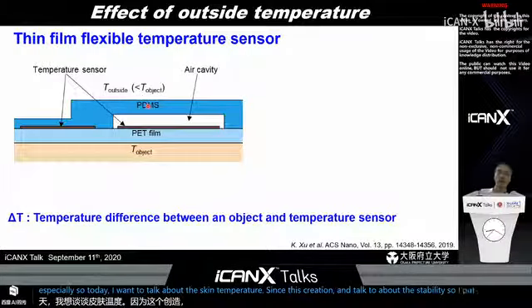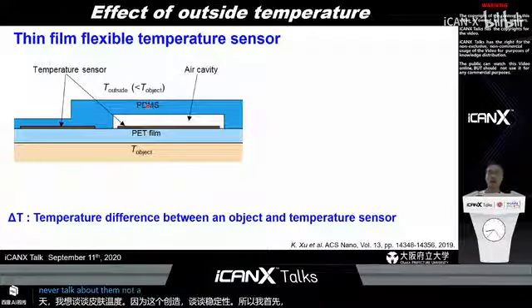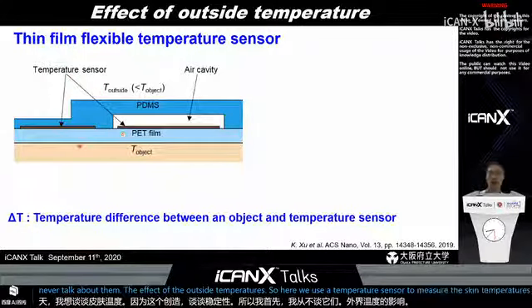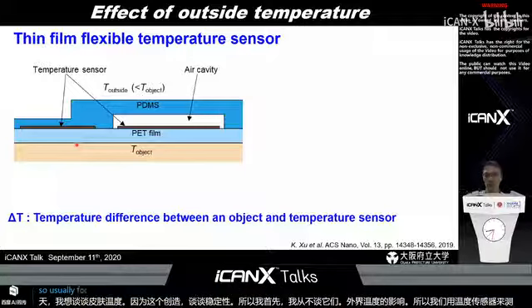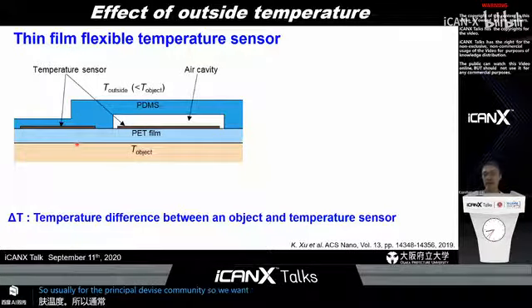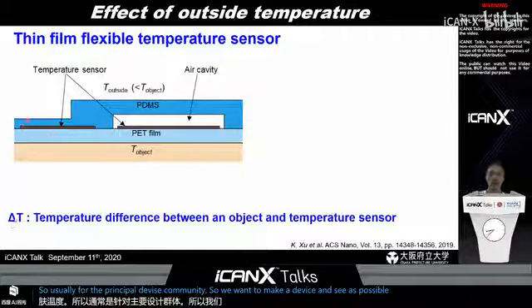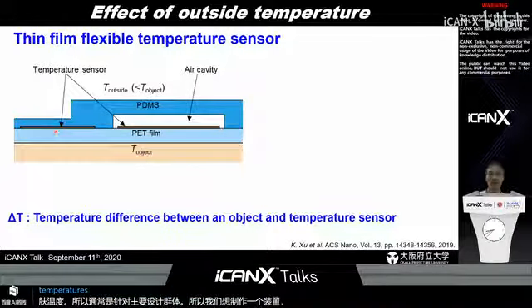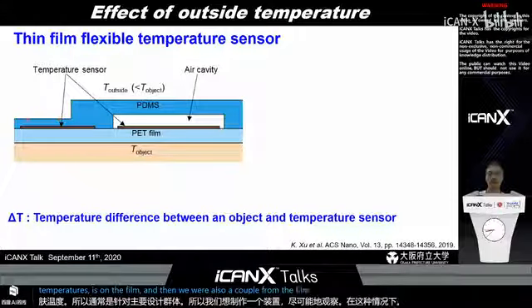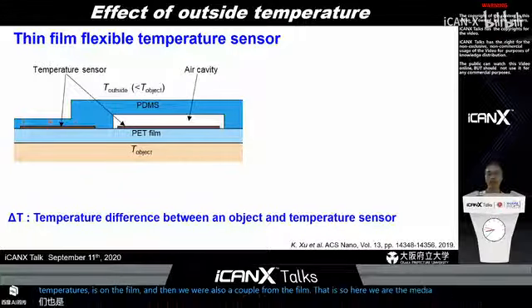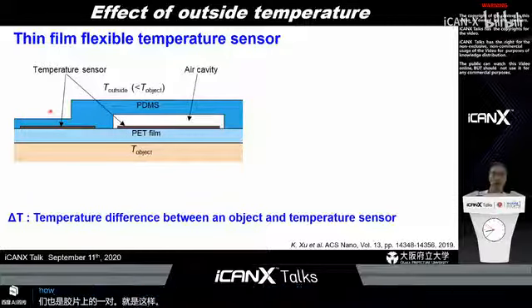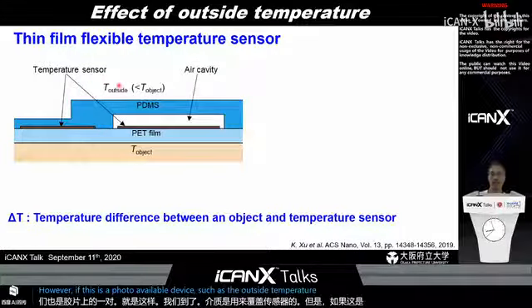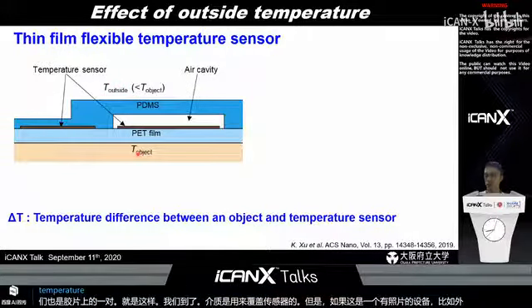So for the first, I want to talk about the effect of the outside temperatures. Here we use the temperature sensor to measure the skin temperatures. Usually for the flexible device community, we want to make a device as thin as possible. In that case, we have some temperature sensor on the film, and then we also cover the film like this. Here we use the PDMS to cover the sensors. However, if this is for the wearable device, actually the outside temperature is easily changed, while the skin temperature is almost no change.